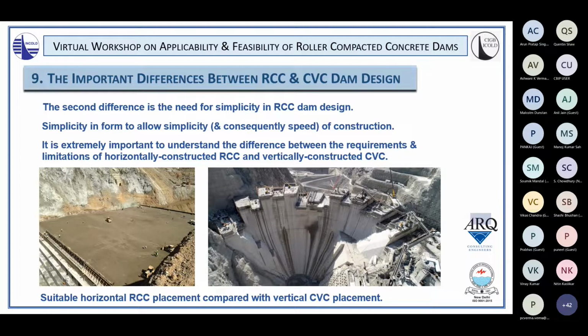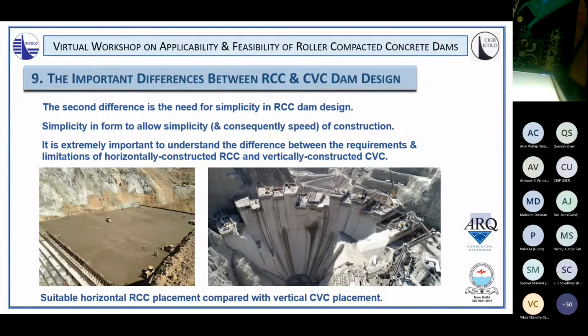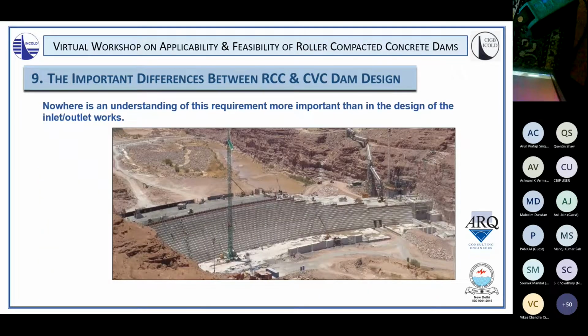That is not the case in an RCC dam. It's quite the opposite. So as soon as you put anything in the middle or anywhere in the structure and you're constructing horizontally, that will interfere with your placement process, and consequently anything that does get included there has to be very rapidly installed. Nowhere is an understanding of this requirement more important than in the design of inlet-outlet works. Get it wrong and you can easily get a situation where the tail wags the dog.